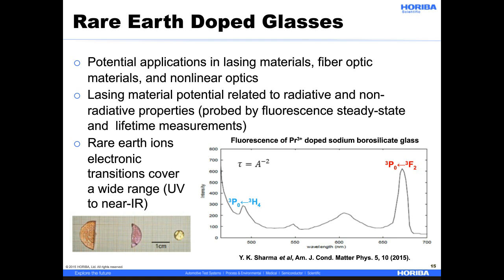The transition at 672 nanometers has a particularly large value for the stimulated emission cross-section because of the drop in covalency associated with the environment surrounding the praseodymium ion. Making empirical measurements of the PL lifetimes at each of these electronic transitions would confirm that these two particular transitions are good choices for lasing. For such a study, a system that can seamlessly integrate both steady-state and time-resolved PL in a single platform would be very advantageous.